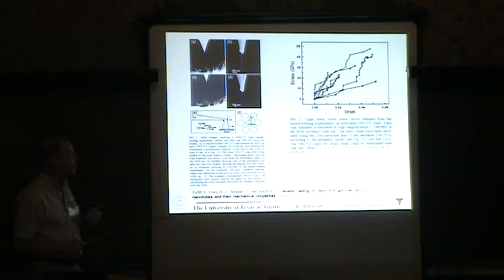And that tearing operation will leave some bundles projecting up that you can try to contact, EBID mount, and then tease out of this sort of yarn material. And again, we're configuring the experiment to be able to apply a load and measure displacement with an AFM cantilever. And when we did so, we ended up conjecturing that this sort of model was sensible where, and you can imagine in this cartoon, I have expanded in-plane, close-packed tubes, but where just the tubes in the periphery were actually being loaded. So we're making measurements in single wall carbon nanotubes and trying to rationalize the mechanical response.